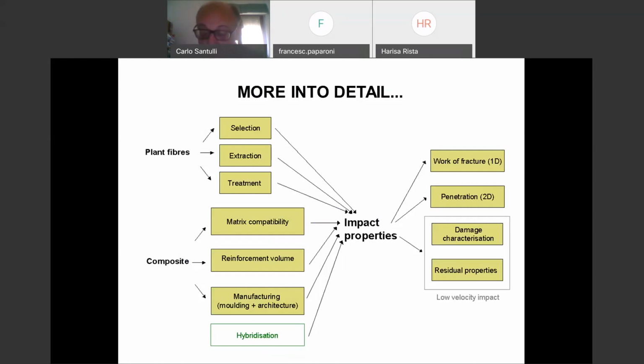Or you can measure the 2D, so by impacting not with a hammer on one line, but with a weight, an impactor, which is a semi-sphere normally, and therefore you can penetrate it or not, can damage it up to penetration, so you see damage on the other side, or you don't, on purpose. You can impact on different energy, with rising energy. You impact with an energy which is not sufficient to induce penetration, but you measure damage and you measure the